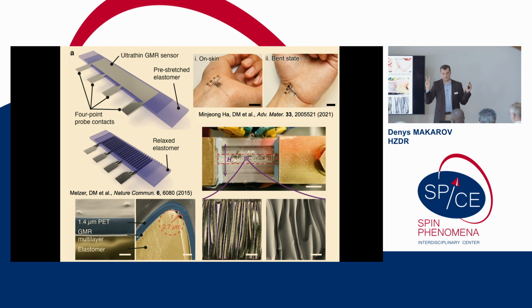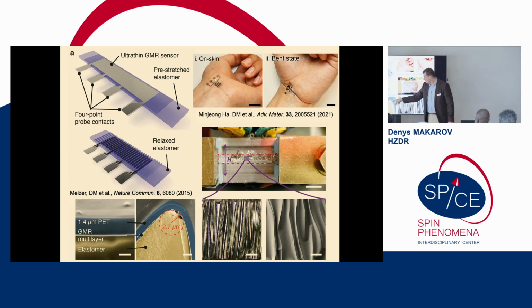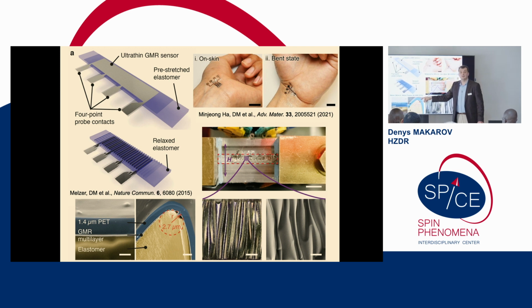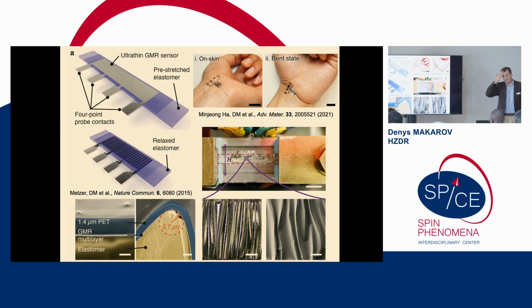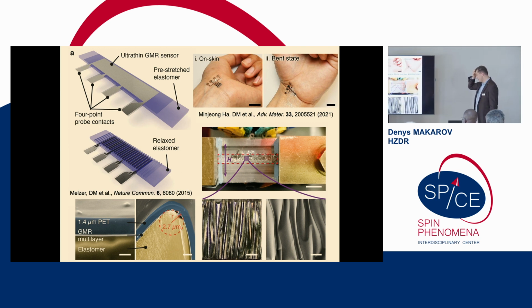There are only two ways to relax strain. One is wrinkling, that's shown here, and another one is rolling, which was shown by Amalio in his talk, right? So there are only two ways a thin film with a thickness gradient, for example, or a strain gradient along the thickness, can relax strain. That's exactly what is happening here. And if you have a look, 100% stretchability will create wrinkles at a level of a couple of microns. And there are even wiggles here which are less than, let's say, a micron. And this is now a very funny puzzle, because when we were submitting this paper, one of the referees asked us, why doesn't it break? Because it's a very natural question.